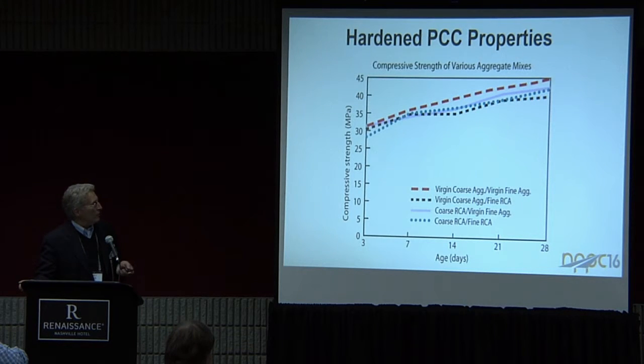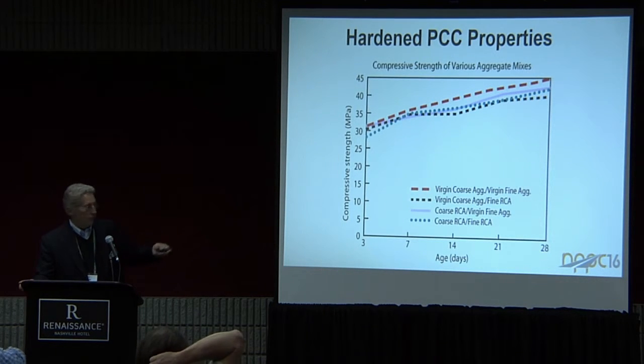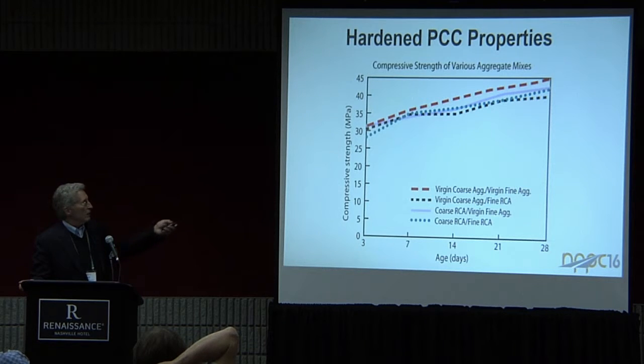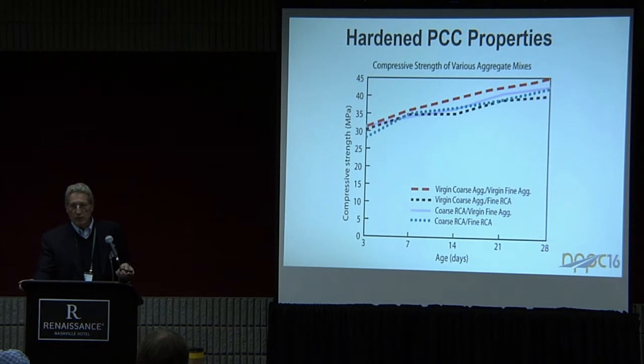This is from that Texas I-10 project. They ran 4 different trial batches, and this is their all virgin mix, and they did this all in metric units here, but 28 megapascals is 4,000 psi. So you're between 4,000 and 5,000 psi for everything at 3 days, whether you used all virgin materials or all recycled materials or half and half recycled and virgin materials for fine and coarse aggregates. So yes, they were all lower. As soon as you introduced the recycled materials, they were all slightly lower strength, but they're all clearly plenty high enough for concrete pavement construction.